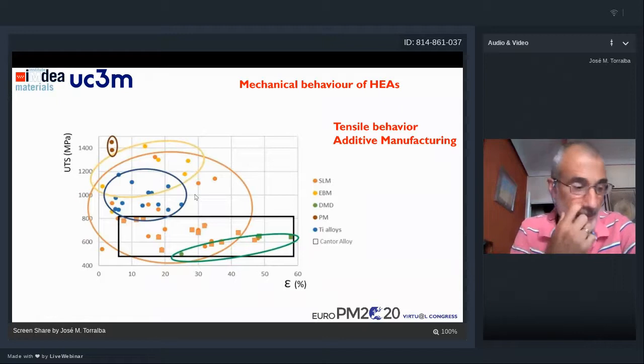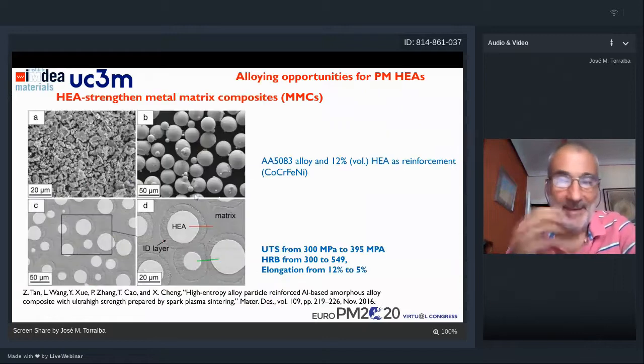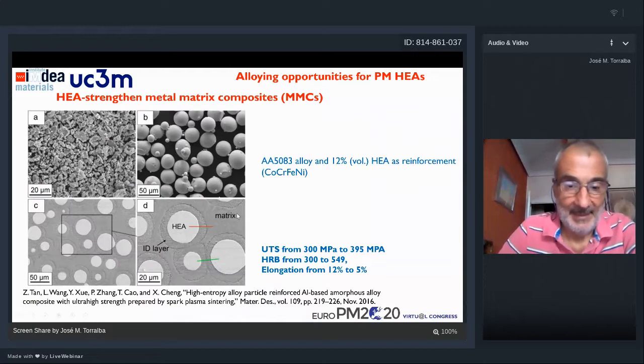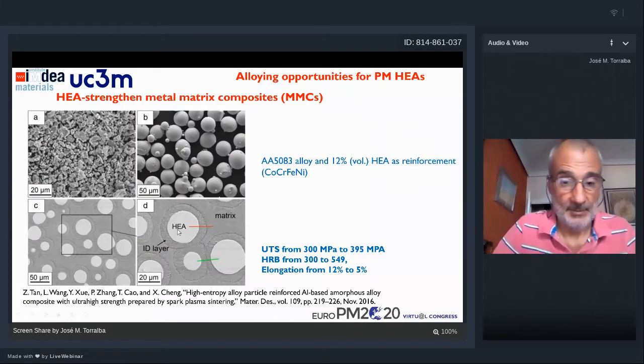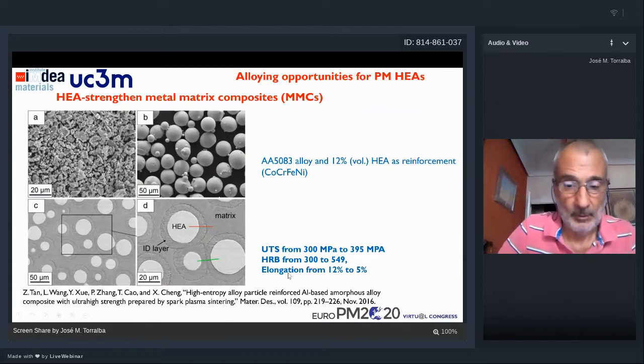So let's go now to explain some special opportunities for powder metallurgy. Here we have the first one. In powder metallurgy, we can mix powders from different natures. In that case, we have a matrix of aluminum alloy. We mix the powders of the aluminum with powders of high entropy alloy, and we can develop a material which is a composite, in fact, in which the reinforcement is the high entropy alloy. So that can give us very nice properties in terms of tensile features, elongation, or hardness.